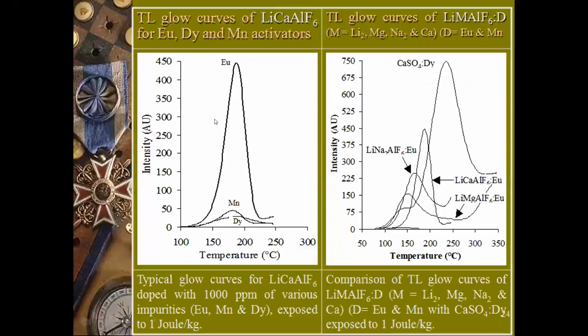But Eu is literally, we are getting our TL glow peak around 200, and that is a single glow peak, which is a symmetrical one. And therefore, LiCaAlF6 performance is advisable. So we have tested this particular concentration. All parameters are being decided thereof.